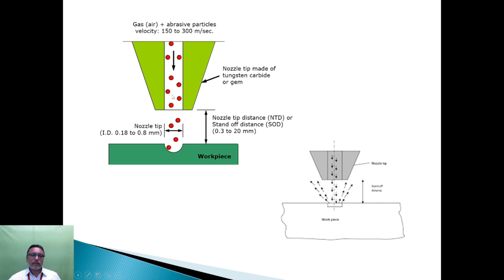When the high velocity abrasive particles impact on the workpiece, the metal is eroded from the surface. After the impact, the particles will rebound back. Then why is the nozzle made conical instead of a square or rectangular shape? The nozzle is the costliest part. It is made of tungsten carbide, gem, or sapphire. When the abrasive particles rebound back, if it is a square shape, they may impact on the nozzle and erode it, and the material is wasted unwantedly. To avoid that, the nozzle is made conical.